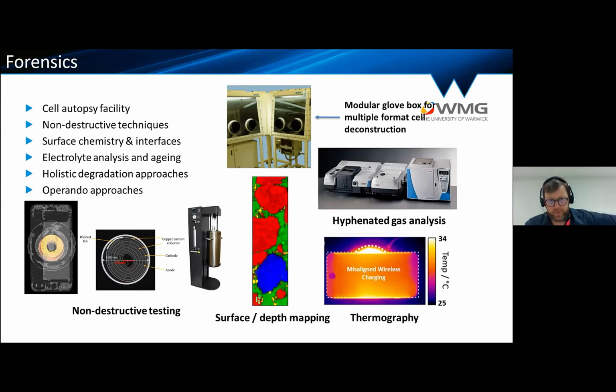So able to simultaneously scan six 21700s, deconvolute into each cell. And as you can see here on the bottom left, the imaging where again you can determine failure modes without having to even open the cell. Because I'm sure, like me, sometimes you worry how much damage you do in opening the cell to evaluate it. So we can actually go past that as well. And obviously a lot of in-depth XRD, in operando XRD, XRF, and microscopy facilities on site as well.